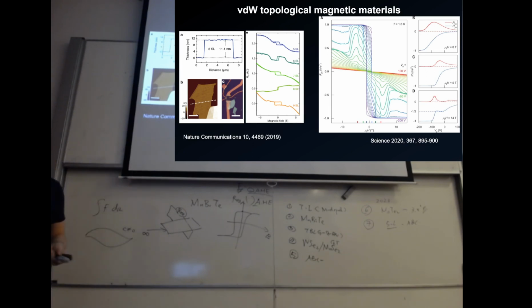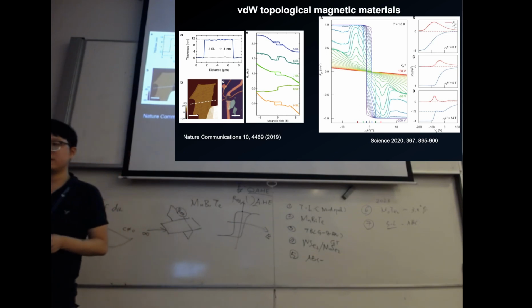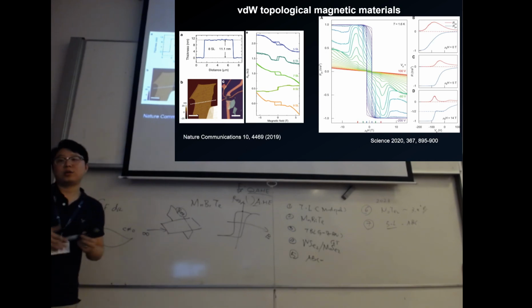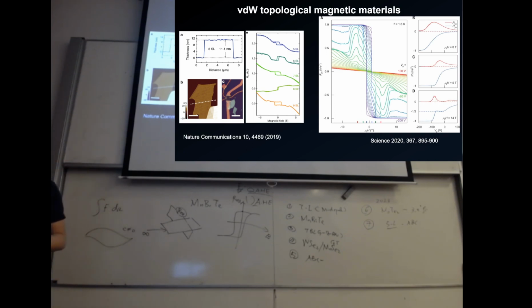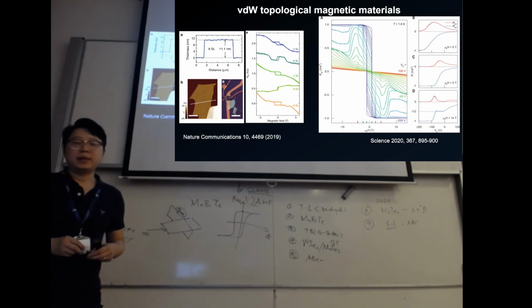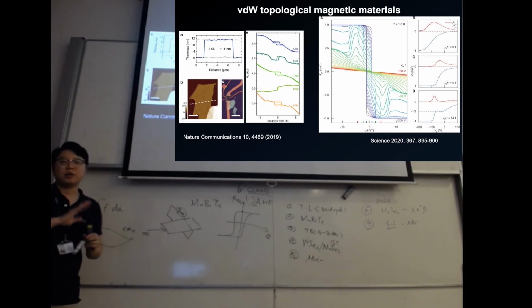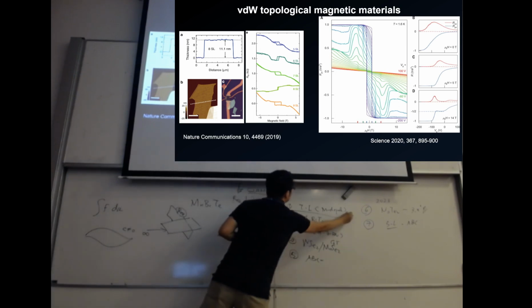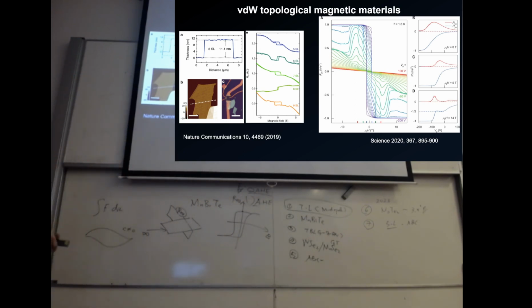One is the conventional one. You need a high mobility, high quality, and the width of the plateau depends on a lot of parameters. But in the topological systems, although they don't require any external magnetic field, they are at very low temperature so far. The highest temperature for realizing these quantum anomalous, integer or fractional ones is below 10 Kelvin. So still very low temperature, and people should continue looking for higher temperature topological orders in any kind of system that can allow us to have more relaxed experimental conditions. But it's already very promising because a few years ago you didn't have many systems. There was only one, a long time ago, where the sample is grown by MBE, which is very rare, and the doping sometimes works, sometimes does not.